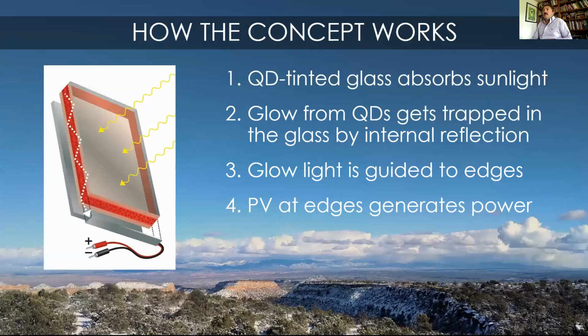So what we do is we tint the glass with quantum dots. The quantum dots are fluorescent. The light that they emit is effectively trapped in the glass. About 70% of the light can be trapped in the glass just by total internal reflection. And then that light gets guided to the edges where you put small solar cells around the perimeter of the glass, hidden out of view, which generates the electricity.